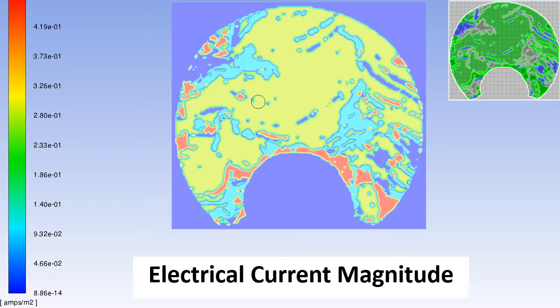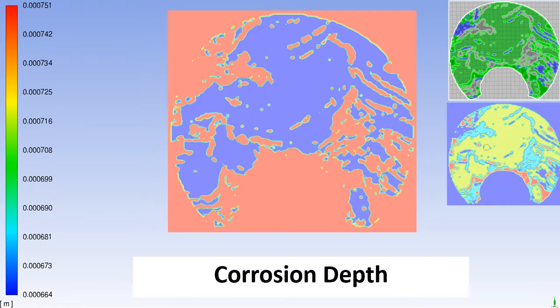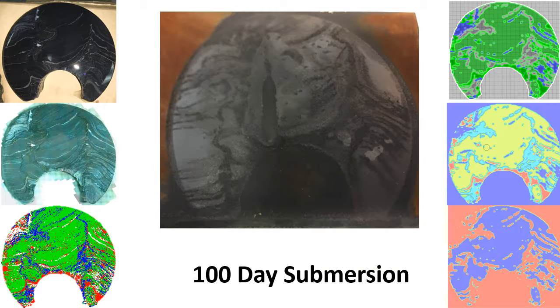Here is a contour plot of electrical current magnitude on the steel surface for sample 19. Here is a contour plot of Z-mesh coordinate on the steel surface representing the corrosion depth at 100 days in the simulation. Here is the steel plate zip-tied to sample 19 after 100 days of submersion experiment in mine water.